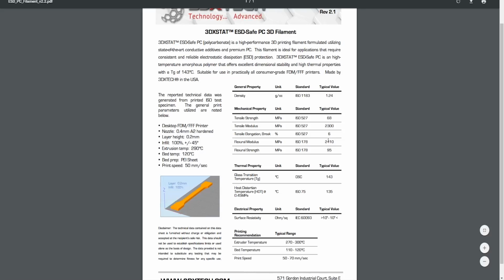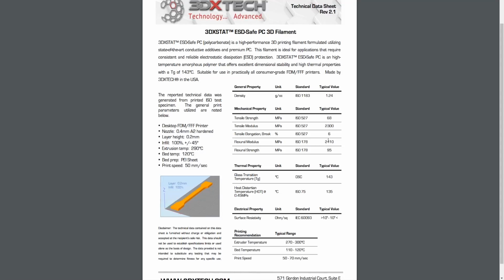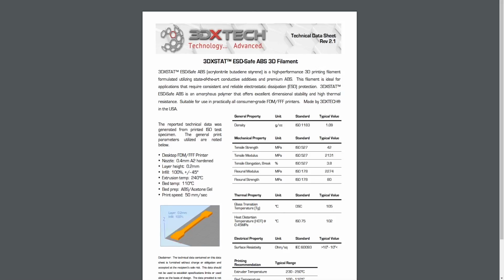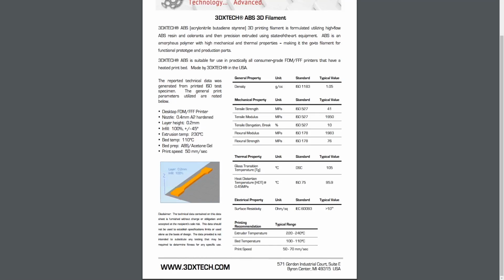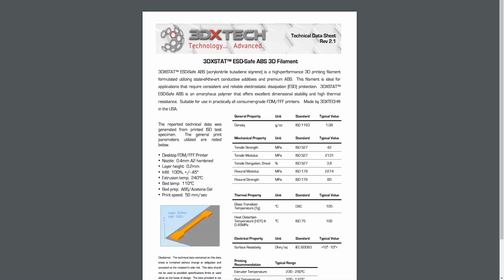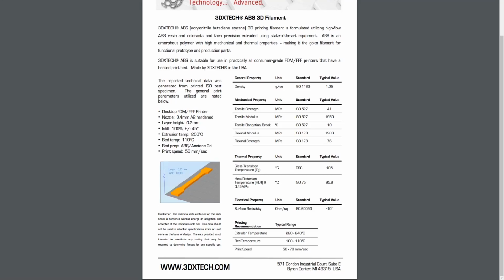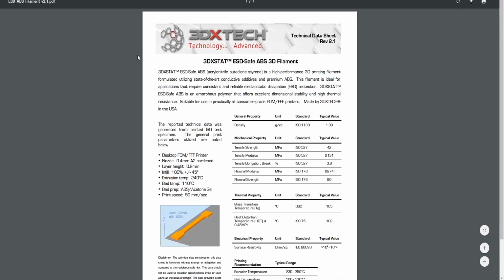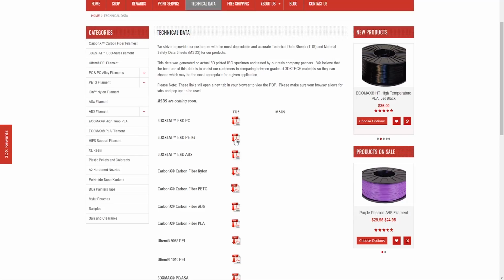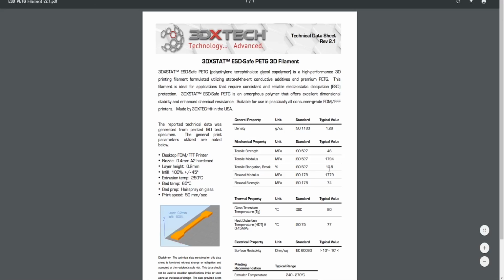The stuff that you add to make it ESD, the electrostatic dissipation protection, or the electrostatic discharge protection, drops the elongation. So here, from the standard ESD compared to ABS, you're dropping by 2.5 times. But you're increasing the stiffness a little bit and not doing much with the temperature. Okay, so that's interesting. So the stuff that you add for the ESD will basically tank your elongation.